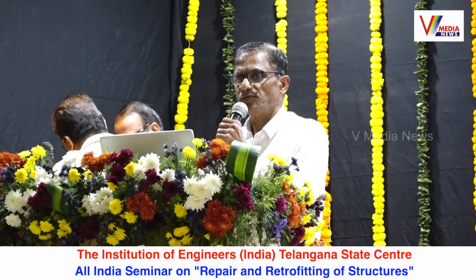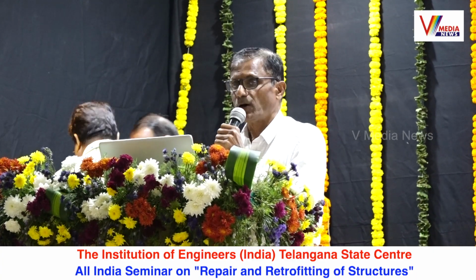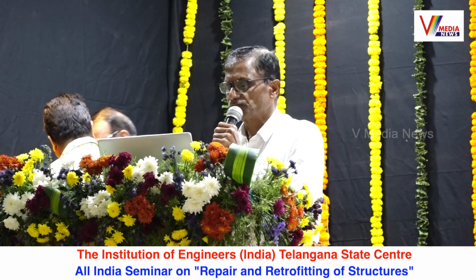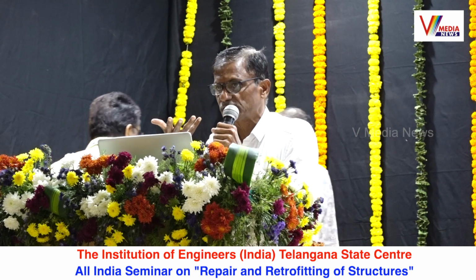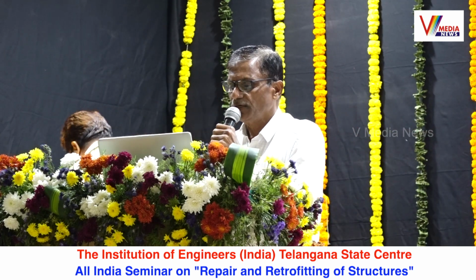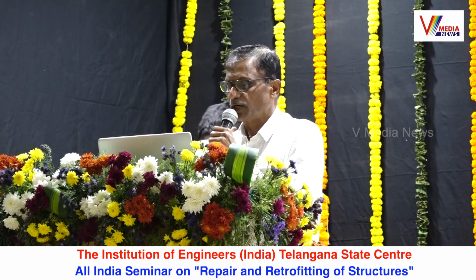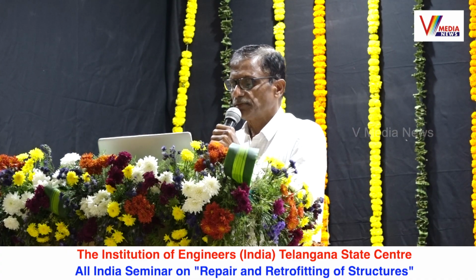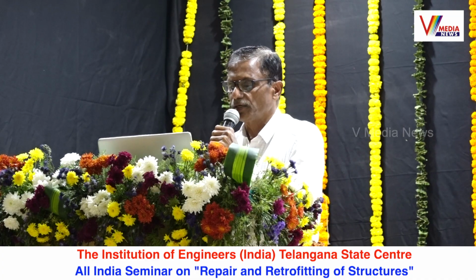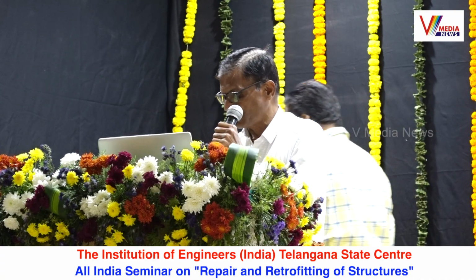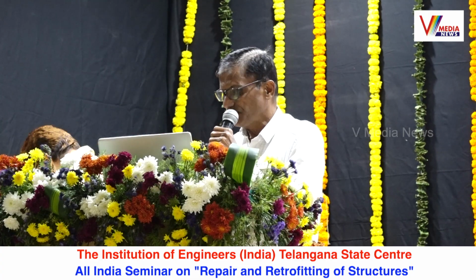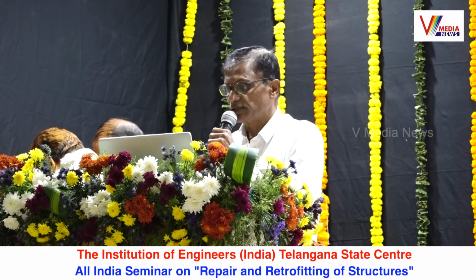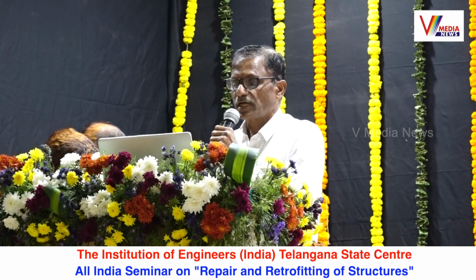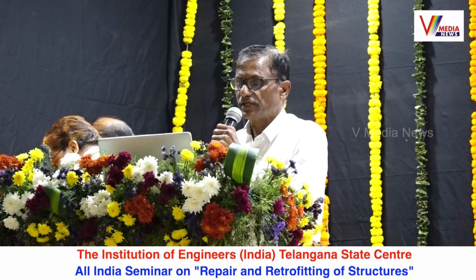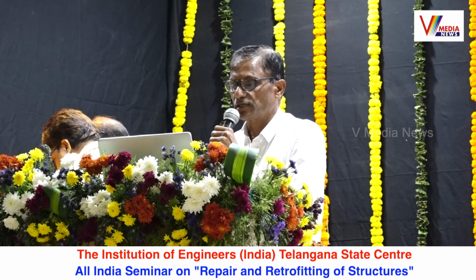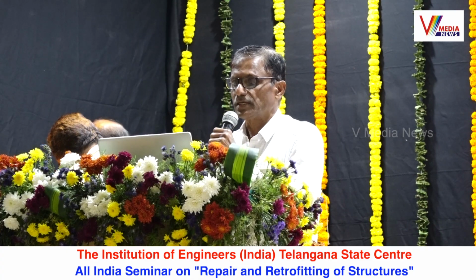So I is the absorption value, and MT is the change in specimen mass, that is the weight of the specimen, and A is the cross-sectional area, the surface area that comes in contact with water. The bottom surface of the specimen is immersed in water up to 2 millimeters. The size of the specimen is normally 100 millimeter by 50 millimeter by 50 millimeter. We measure the time and the weight, and take the difference of that weight. The weight is measured after every 3 minutes, 3, 6, 9, and so on, up to 60 minutes.